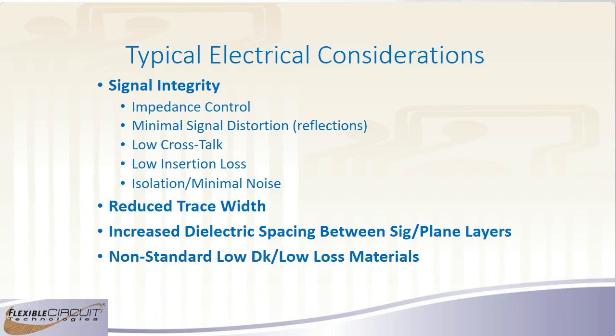You can use non-standard low dielectric constant and low loss materials, and until very recently, those materials were limited to some very difficult materials to process. They were thermoplastics like LCP or Teflon, and they processed at very high temperatures. Typically, you had to laminate them over 300 C, which put it out of the reach of most flex circuit manufacturers just because the equipment typically doesn't go up to those temperatures for standard materials, and so you really limited your vendor base. More recently, they have introduced some low loss materials that do process at more standard temperatures. They are more expensive, but it does give us another option to be able to get some of the requirements that we need without making them a lot thicker and not go into a really strange material.